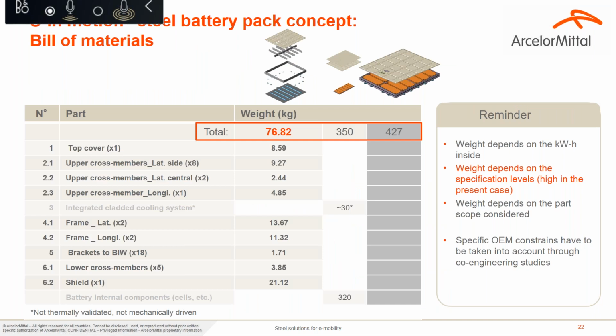So we end up with weight. As I said at the beginning, this weight doesn't come from nowhere. Of course, it depends on many parameters, as I mentioned. You will find here the bill of material with the weight of the different parts. Again, if you have more weight of cells or less weight of cells, this weight of steel, this 77 kilos, will evolve. And as Jérôme said at the beginning, we are able to take into account your specific constraints and adapt to find the best solution at the best weight.